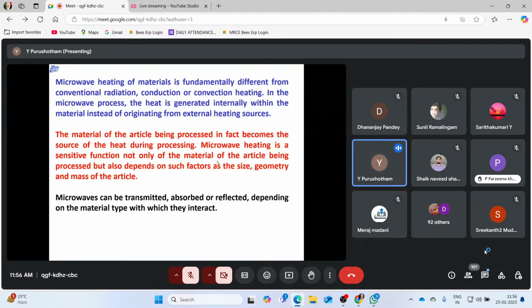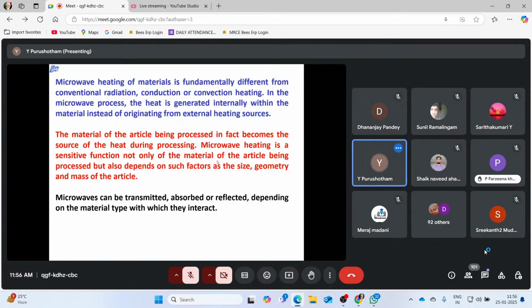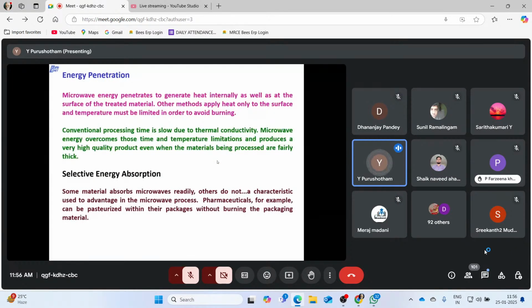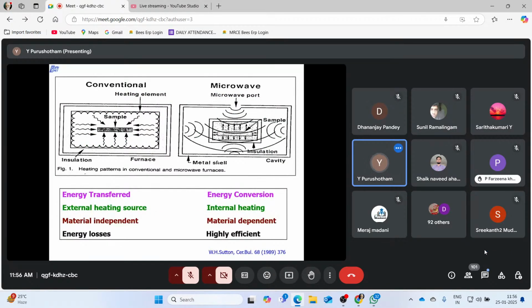Whereas in microwave, it will immediately reach your set value, and once you switch off the microwave source, it will automatically come down to room temperature within a very short time. So the exposure time is reduced like anything. These microwaves can be transmitted, absorbed or reflected depending upon the material type with which they interact. So this process is 100% material dependent. Energy penetration and absorption take place. So this is conventional and microwave heating.